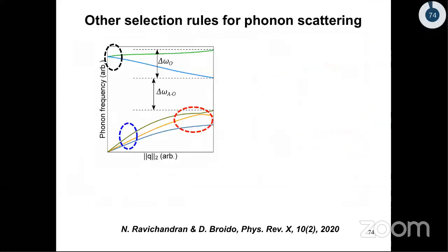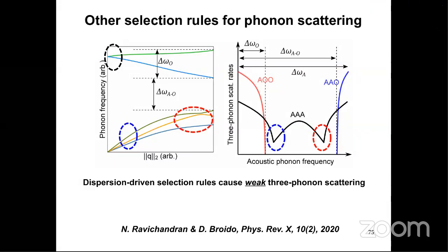Yeah, so that was the motivation for this work. We wanted to get some insight just by looking at the phonon dispersions, whether we can predict a material will have strong 4-phonon effect or not. So this paper contains these selection rules that are related to the joint density of states, and you can identify based on just the dispersion which of these scattering channels will have anomalously weak joint density of states.